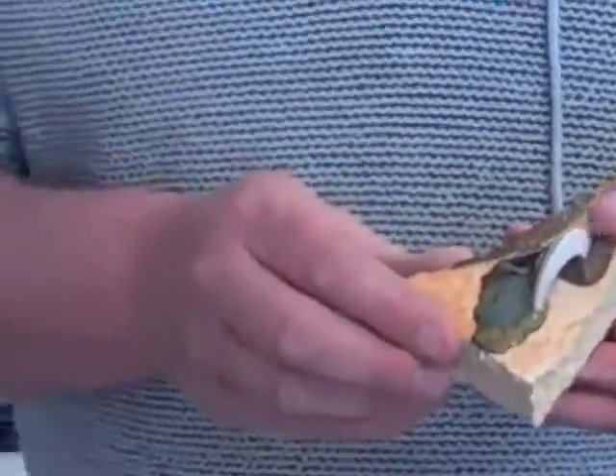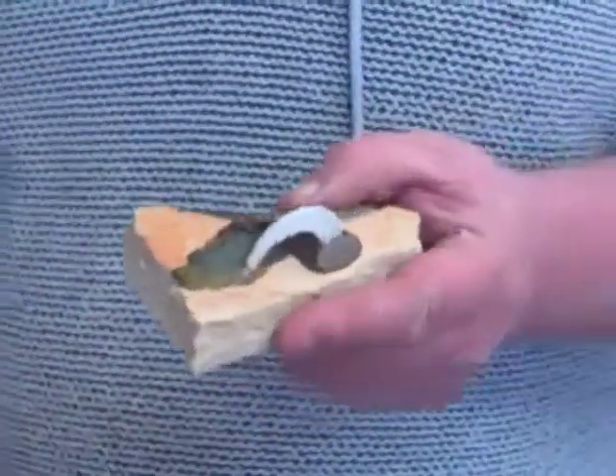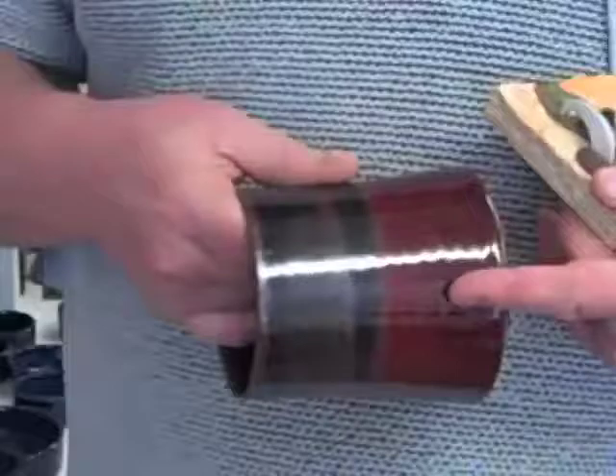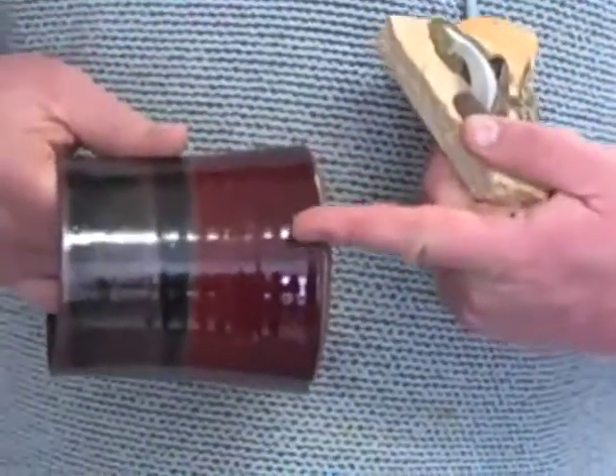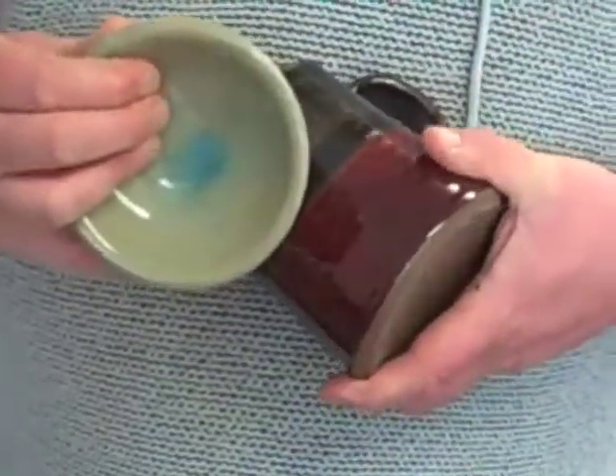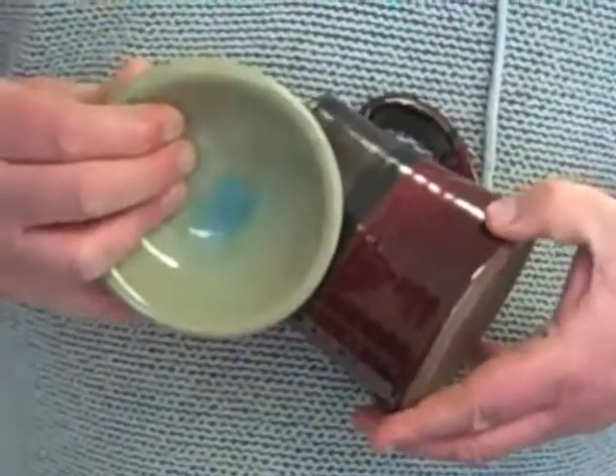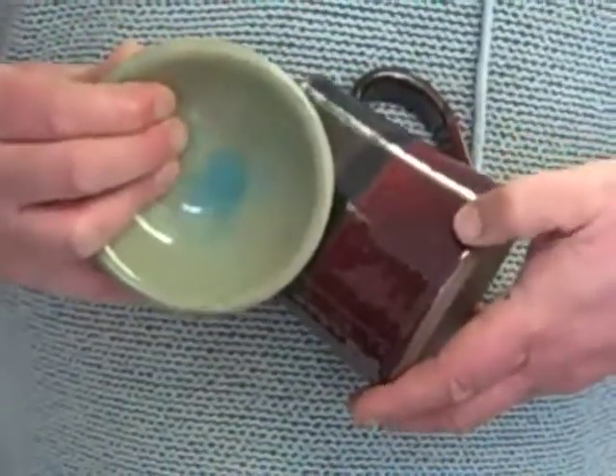Now the results we've got from that kiln are copper reds, which is like that, which you wouldn't get in an oxidised atmosphere. In an oxidised atmosphere, that same glaze comes out that colour. So just by starving the oxygen in the kiln brings out the red from the copper.